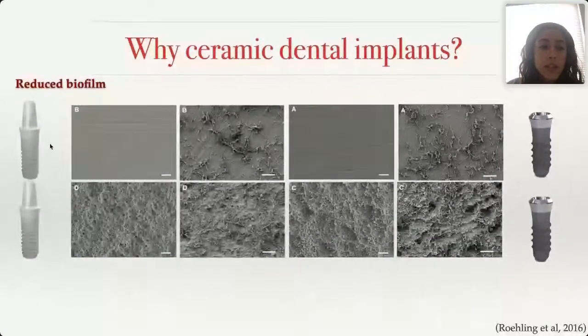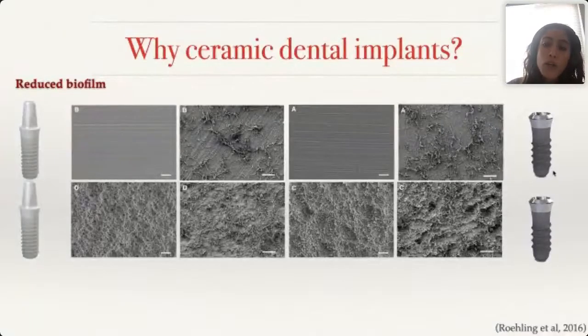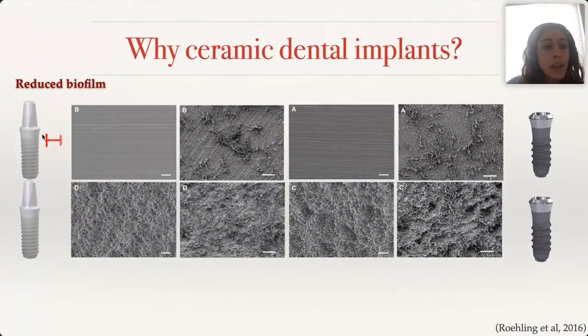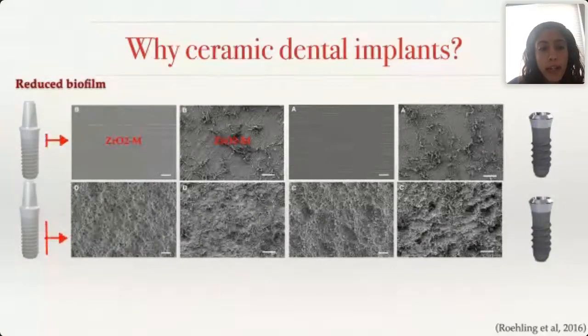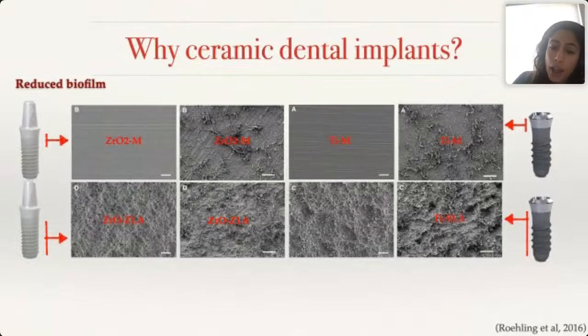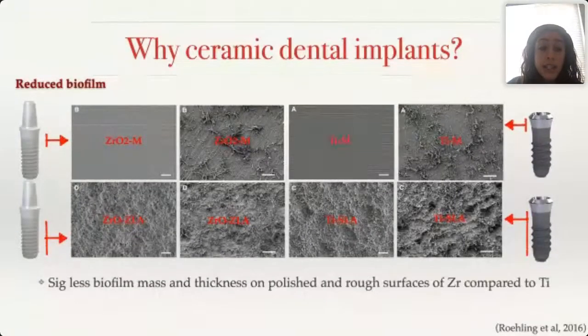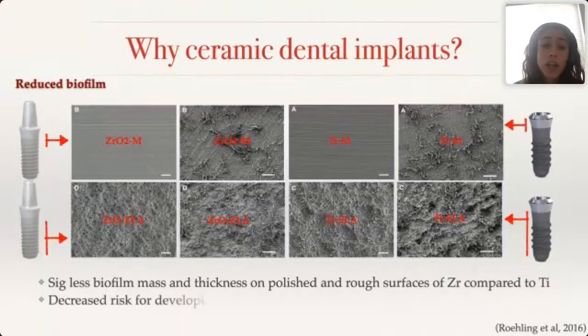This is a study using the pure Straumann ceramic implant and a tissue level Straumann titanium implant. They had discs of the machine surface area and cultured bacteria over the disc, before and after culturing, and then the sandblasted and acid etched surface was also cultured with bacteria. They compared these to discs from titanium with bacteria cultured on the machine surface and on the sandblasted acid etched surface. This study found significantly less biofilm mass and thickness on polished and rough surfaces of zirconia compared to titanium.